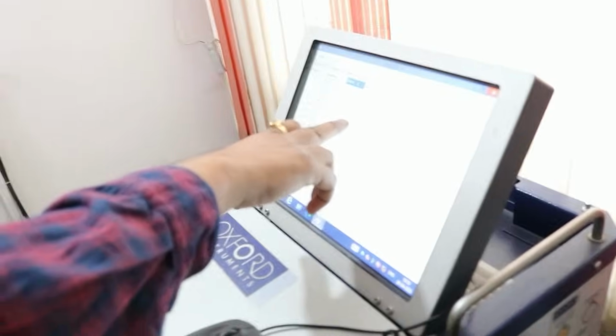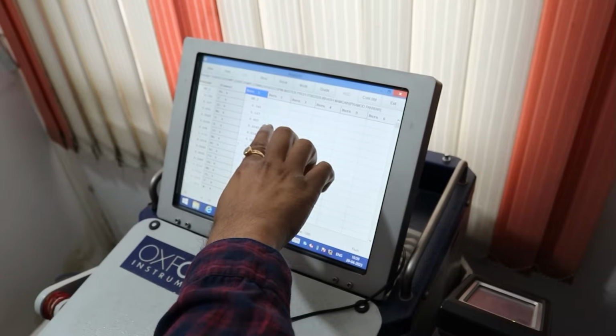Here we are going for different elements. Specifically we look for carbon, because basically the hardness depends on carbon and chrome. So its carbon is like 0.75. For 1080 there's a tolerance of 0.05. So it goes to 0.75 and then 0.85, that's a grade of 1080. And then we check for chrome, and chrome is also like here it's 0.1. And then the manganese. There's actually three special elements that we have to check: carbon, manganese and chrome. And once they are fine, then we approve the steel and put it in the production.